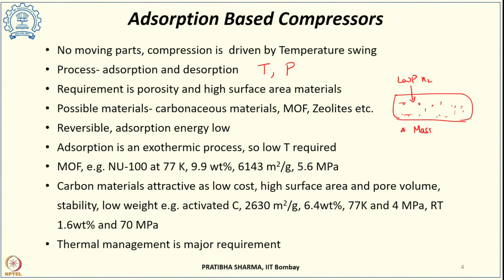The maximum achievable pressure from such devices depends upon the mass of adsorbent used, the final temperature supplied, and the volume available for the bulk gas. An important requirement in adsorption based compressors is high surface area materials with porosity, because the rate of adsorption depends upon the high surface area of the bed.